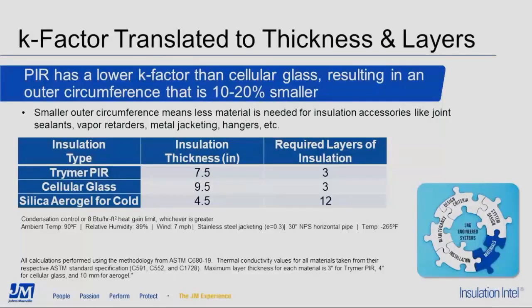For the PIR and cell glass, there are 3 layers needed. However, even though the total thickness required for the aerogel is the smallest, the number of layers that have to be each individually installed is 12, 4 times the number of layers for PIR and cell glass. The reason for this is that the aerogel comes in a maximum layer thickness of only 10 millimeters, which is less than 1/2 an inch.